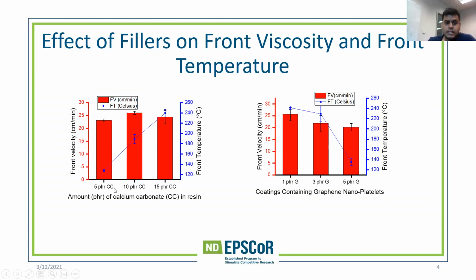And we also see that by increasing the amount of calcium carbonate, we did see an increase in the front temperature because calcium carbonate provided a masking effect and doesn't let the heat escape. The front velocity was not much impacted.